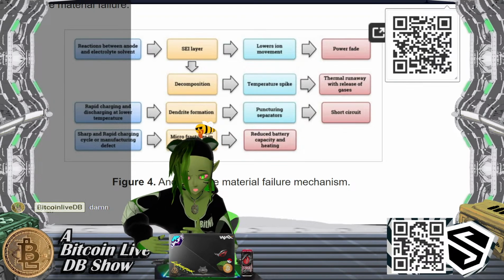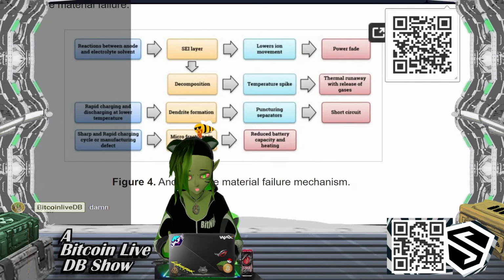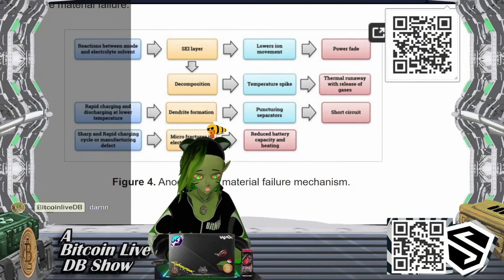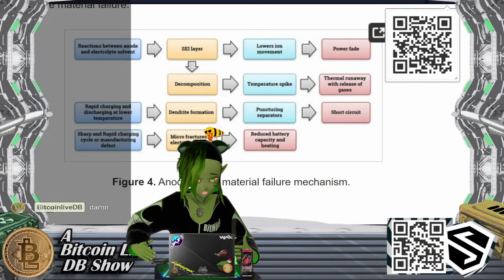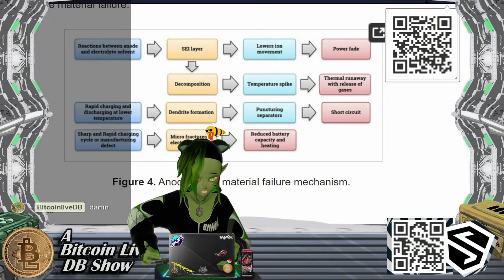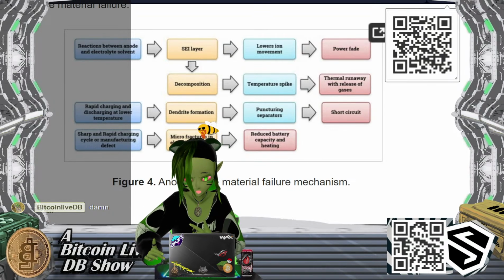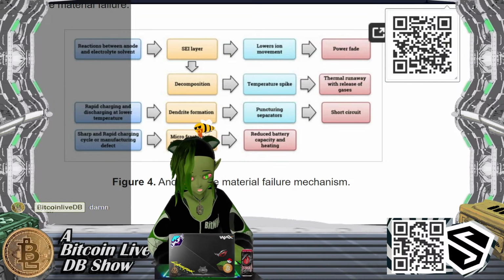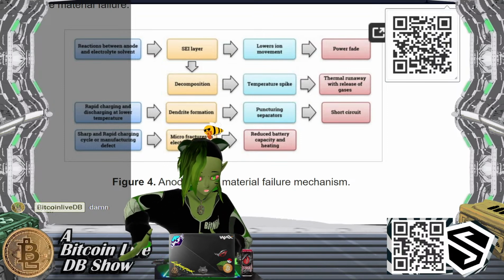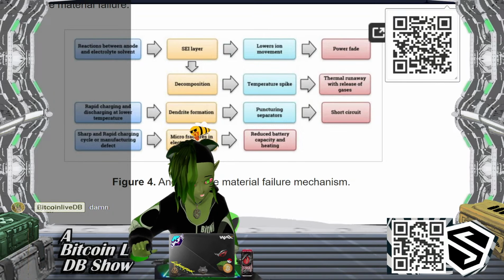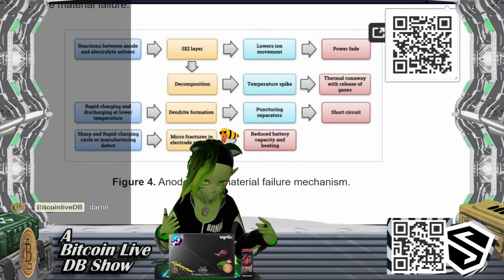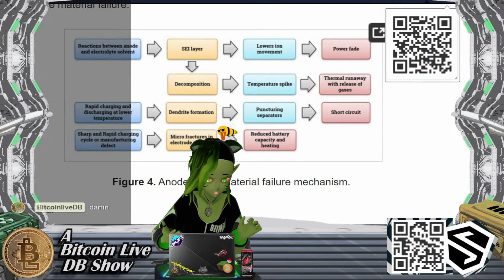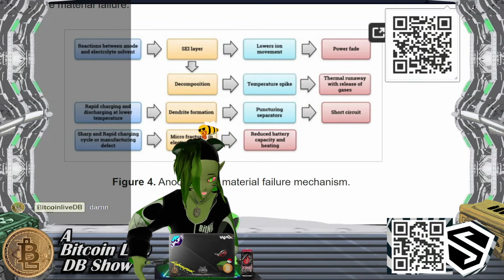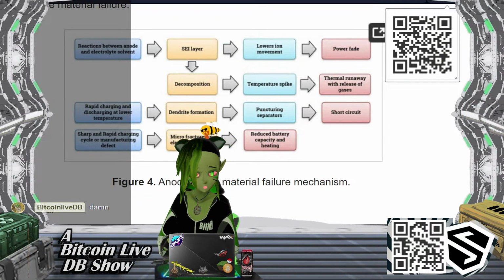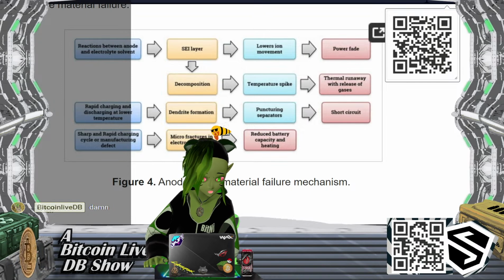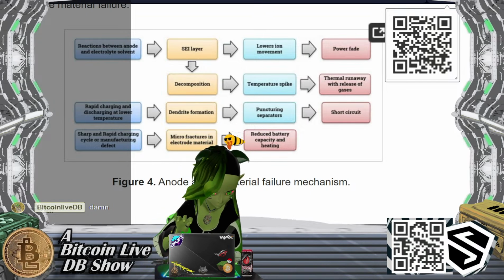If we have sharp or rapid charging cycles or manufacturer defects, so basically if we're charging the phone a lot and using the phone a lot and maybe not letting it get closer to dead, maybe not letting it down to like 15-20%, maybe you're recharging it at like 50-75% or something like that. So you're charging a lot, you're constantly going through it, you're constantly keeping it on and stuff, or general manufacturer defects like we saw in some of those Note 7s. Well, you have microfractures in the electrode materials, which turns into reduced battery capacity and increased heating during use, which in turn can become thermal runaway.